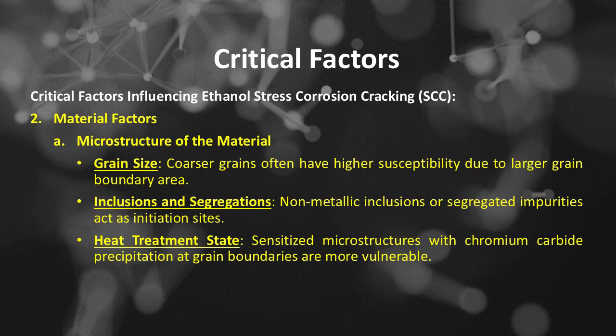Number 2 is material factors, which include number A, microstructure of the material. Grain size: coarser grains often have higher susceptibility due to larger grain boundary area. Inclusions and segregations: non-metallic inclusions or segregated impurities act as initiation sites. Heat treatment state: sensitized microstructures with chromium carbide precipitation at grain boundaries are more vulnerable.